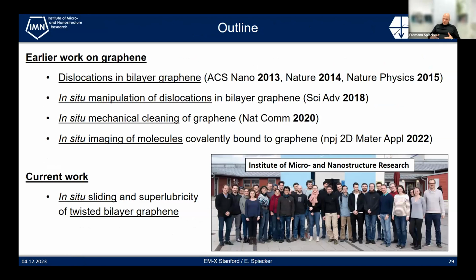I hope that I could show you that, based on our earlier investigations of dislocations in bilayer graphene and their manipulation, we now moved on to the in situ sliding of a whole network of dislocations, or in other words, a twisted bilayer graphene, and how these dislocations evolve. I could show that a twist angle is introduced by sliding and leading to superlubricity in the sliding action.